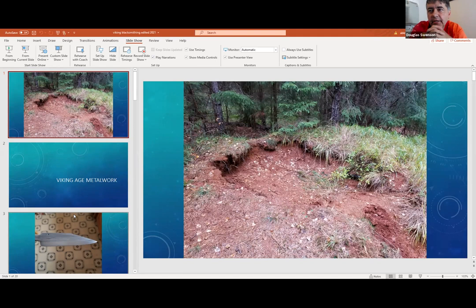To refine this, they would build a small furnace of clay, maybe 3 feet tall and maybe 10 to 12 inches in diameter. They might load that furnace with maybe 80 to 100 pounds of the iron ore with a combination of charcoal. The fire would be blown with those bellows, the double bellows that we were just looking at, getting an extremely high temperature with a chemical reaction taking place: the charcoal producing carbon monoxide, carbon monoxide combining with the iron oxide to reduce it to a pure state of metallic iron.